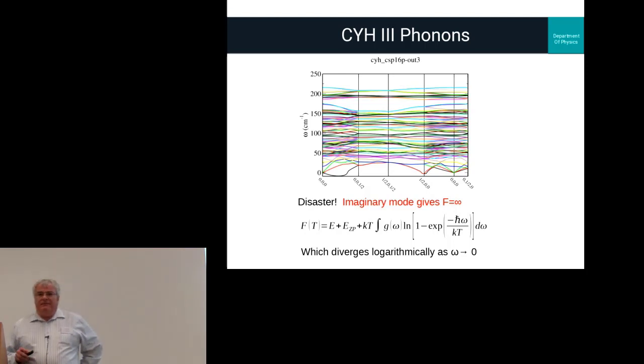How do we calculate the free energy from that? This is a complete and utter disaster, because here's our formula for vibrational free energy. It's the integral of the phonon density of states times log of 1 minus e to the minus beta h-bar omega, this Boltzmann factor. As the frequency goes to zero, the exponential goes to one, the argument of the logarithm goes to zero, so the logarithm diverges and the free energy diverges. What can we do? I've seen calculations in the literature which simply discard these modes. But what you're doing is not discarding small components to be ignored; you're discarding the very largest contributions to the free energy, because it's the low frequency modes that contribute the largest vibrational entropy. This is what you want to know most and what you can find out is the most difficult numerically.